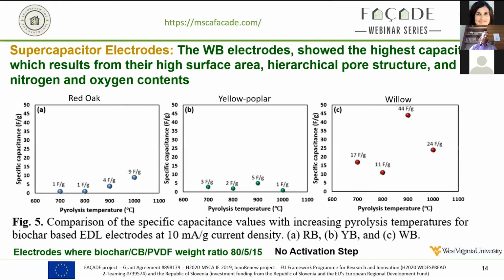So this is the same biocarbon which I showed before. Before, the red oak performed the best in conductivity. But in this case, in terms of capacitance, the willow, which had the highest ash content and the lowest carbon content, actually did the best. So here we're at 44 farads per gram, and I mentioned those ones for sale were around 28, if I remember right. This research was done by including these carbon materials as electrodes in coin cell batteries, and these capacitance tests were done. So no activation done here.